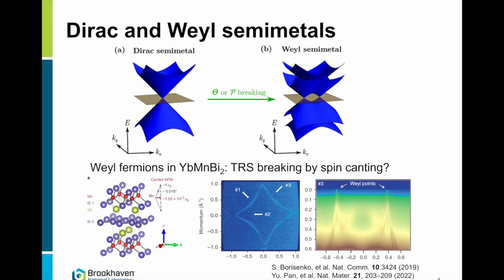And in fact, it was reported from ARPES measurements. So this is the ARPES measurement of a Fermi surface, actually. The Dirac cones are here, they're strongly anisotropic, so this velocity is shallow and this velocity is high. So these Dirac cones in the measurement look almost like a nodal line, but actually these are 4 Dirac cones. These are cuts this way where velocity is strong, and they have somehow seen the splitting of these Dirac cones into what they postulated to be Weyl points.